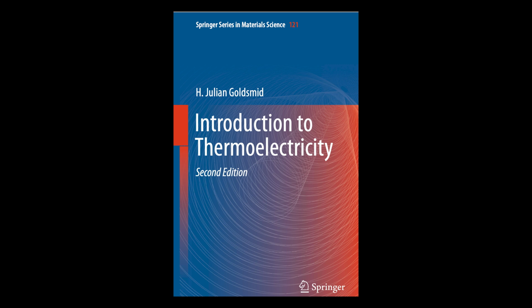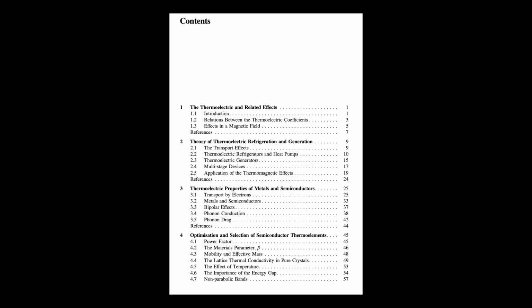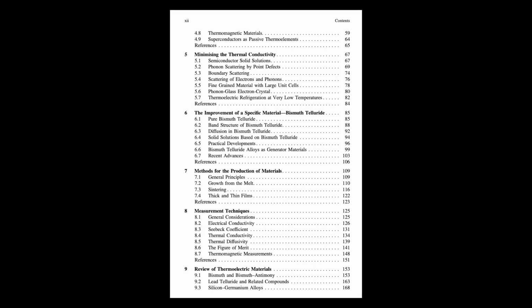And finally here, superconductors as passive thermoelements. That sounds intriguing. It is. The idea is to leverage their zero electrical resistance below their critical temperature. Great for cutting Joule heating losses. But to be useful as passive parts like connectors, they also need low thermal conductivity. Don't want them shorting the temperature difference. And high critical current density. Need to carry current without losing superconductivity. The example I mentioned is pairing a high Tc superconductor with a conventional thermoelectric like bismuth. The superconductor acts as a super efficient electrical path, potentially boosting overall system performance, maybe especially if a magnetic field is also involved.